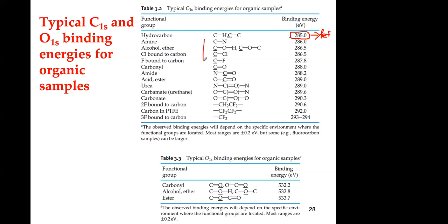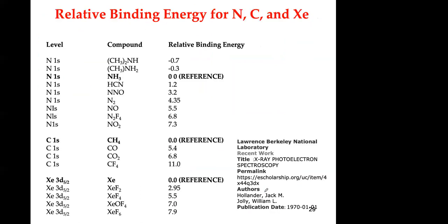But here you can see that as the atom that is binding to carbon is more electronegative, the binding energy increases. And it's a very easy way to look at structures or corroborate structures of your material. The same is true with the oxygen 1s signal. The difference is not as high as the carbon 1s, but the oxygen 1s also changes depending on what is binding to the oxygen. So you can look at that very easily.